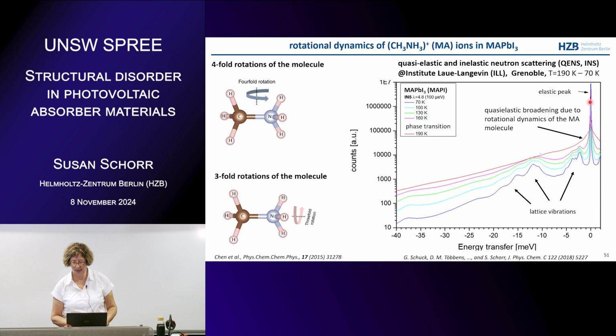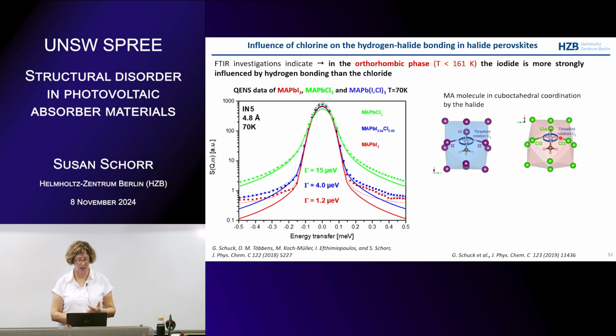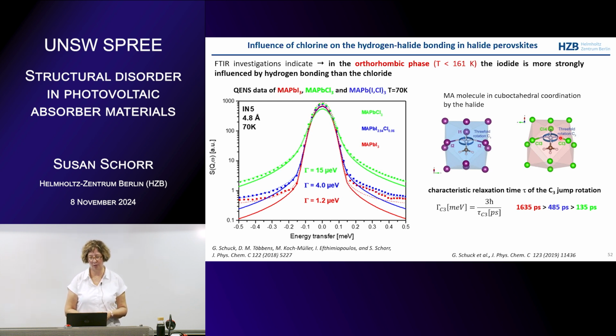And this sharp peak here is in principle the Bragg peak. So this is the elastic scattering where you have no energy change. And then you see here a broadening of this peak at higher temperatures, which then gets a little bit lower if you decrease. And if you decrease more, you also see the lattice vibrations coming up here. This is then the inelastic scattering, and you can also measure phonons with neutron scattering. And from analyzing this quasi-elastic broadening, you can get information about the characteristic relaxation time of these jumps.